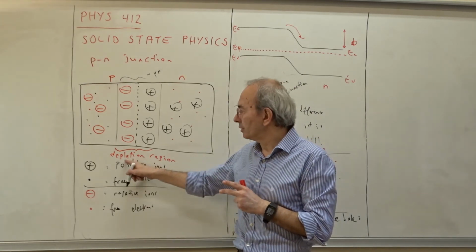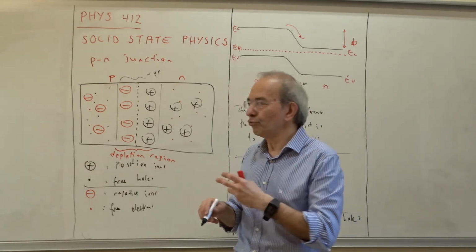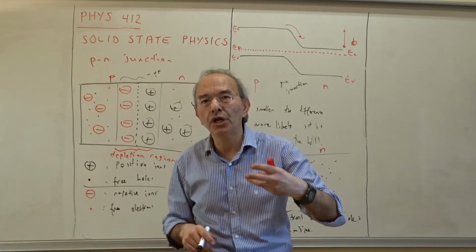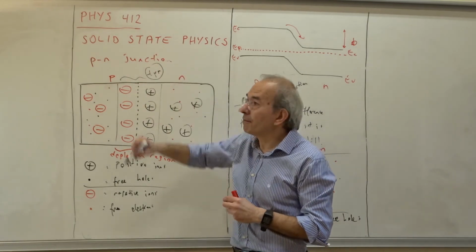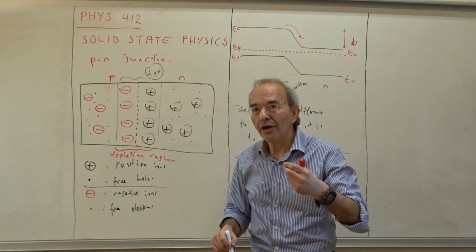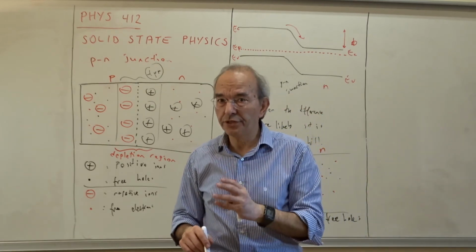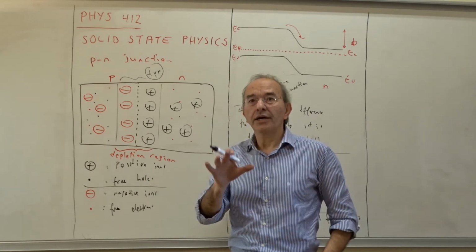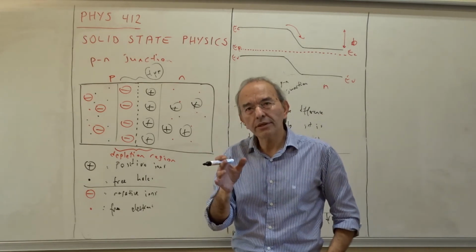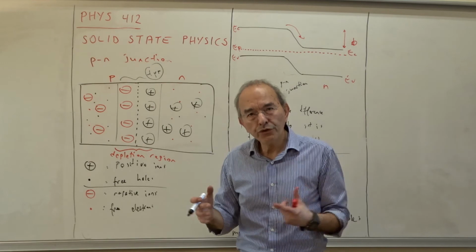So this is the whole depletion zone, depletion layer, depletion region. It has a thickness of around, let's say, 1 micrometer, a 1,000th of a millimeter, a very, very thin region. All right, but on the other hand, there are ions. Ions are not influenced by this diffusion.